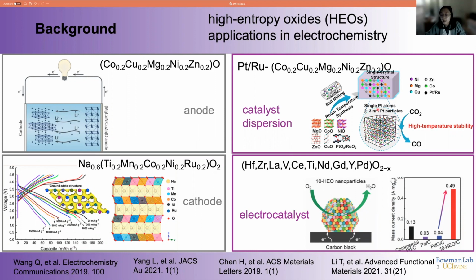Catalyst platinum atoms can be distributed uniformly in the HEO matrix because of the composition stability, and the cations have this uniform distribution in the cation sites. Because HEOs have high temperature stability, this catalyst shows high efficiency in carbon dioxide conversion.